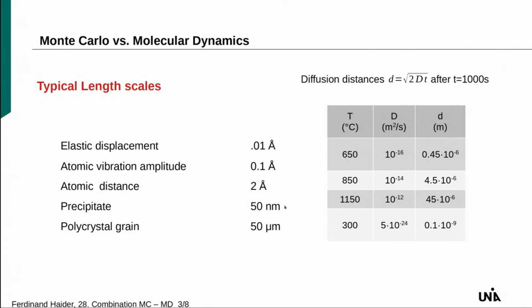Precipitates, what you normally use for peak hardening if you are doing artificial aging. You have sizes in the range of 50 nanometer, depends on the alloy, perhaps 100 nanometer, but typically not micrometer or so. The grain in polycrystal is 1,000 times larger. That's this scale.